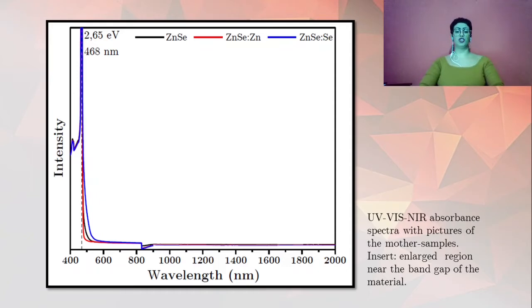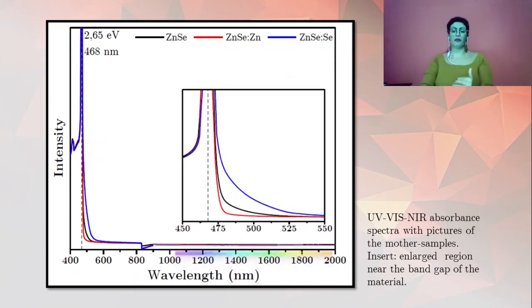The absorbance measurements of the model samples corroborate the fact that there was no evidence of the existence of intrinsic or extrinsic defects, since absorbance bands were not observed within the band gap of the zinc selenide. The only difference between the spectra of each sample is the behavior close to the optical gap of the material at approximately 2.65 electronvolts. This behavior can explain the different colors of the samples, which may be related to the formation of selenium clusters during the growth.